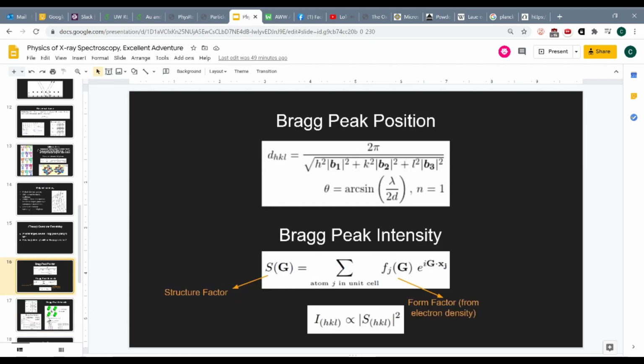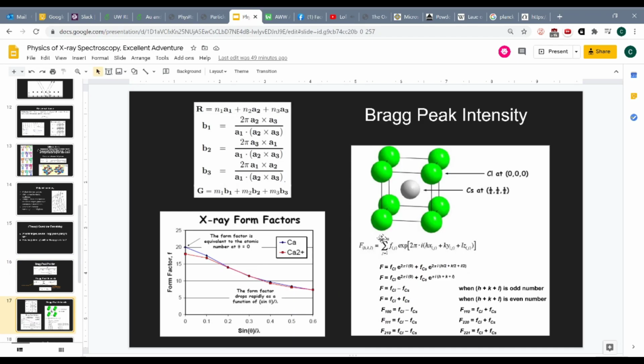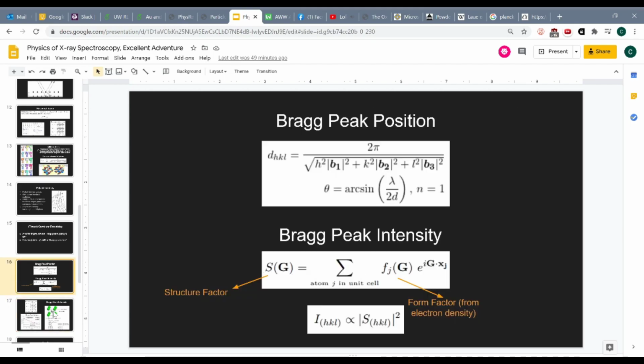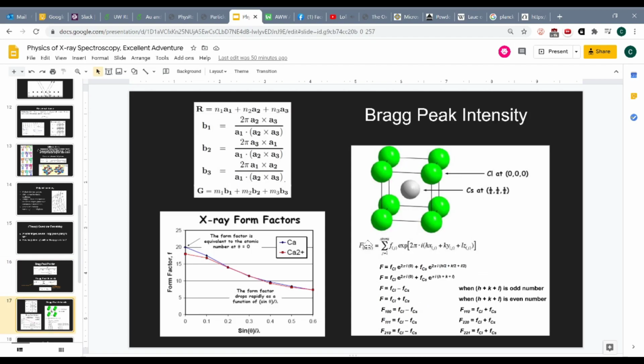And if we wanted to actually calculate what the structure factor is, what the square root of the magnitude would be for a particular example, we have here chlorine cesium, which is a body-centered cubic 3D structure where we have chlorine at every corner and then one atom of cesium in the middle. So it's at the 1/2, 1/2, 1/2 position. There are a few different standards. Here they use F. Back here we use S for the structure factor, but keep in mind this is just the structure factor. And as I said, it's defined for some HKL values, which are our integer reciprocal lattice coefficients.